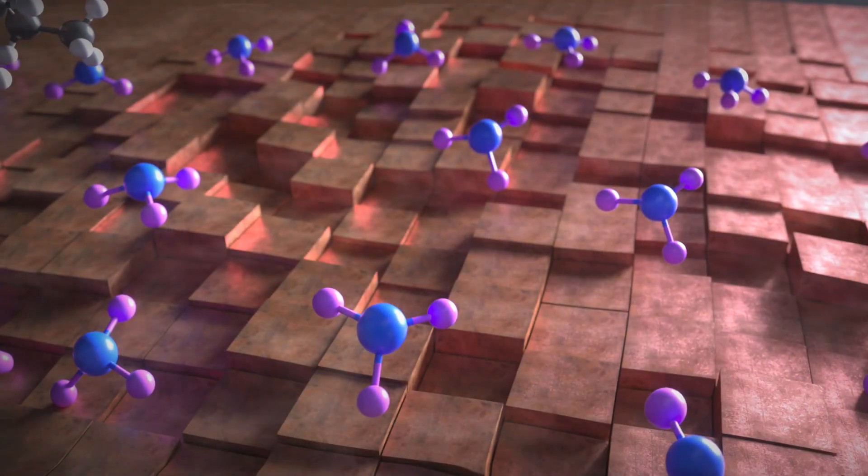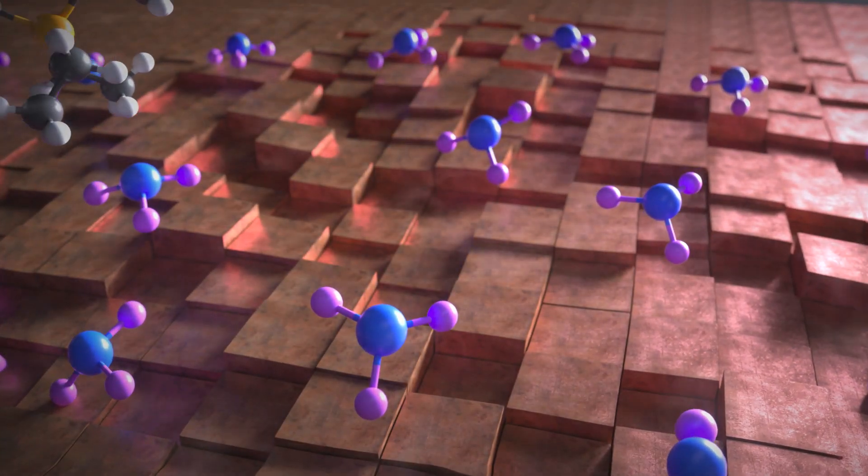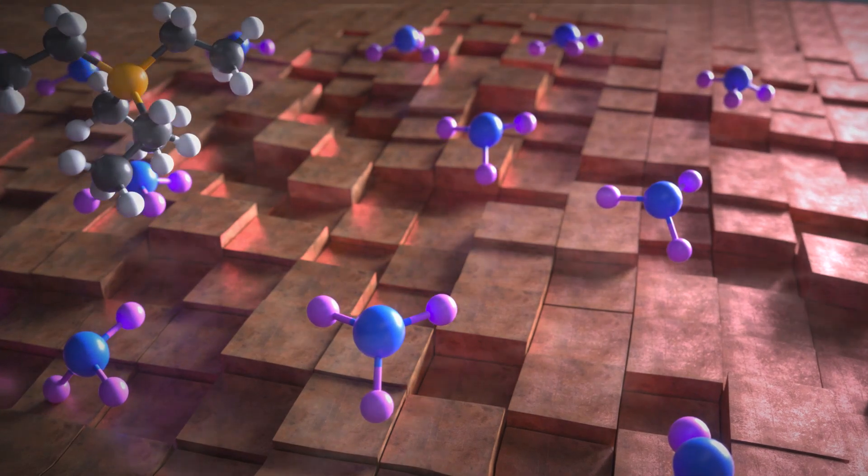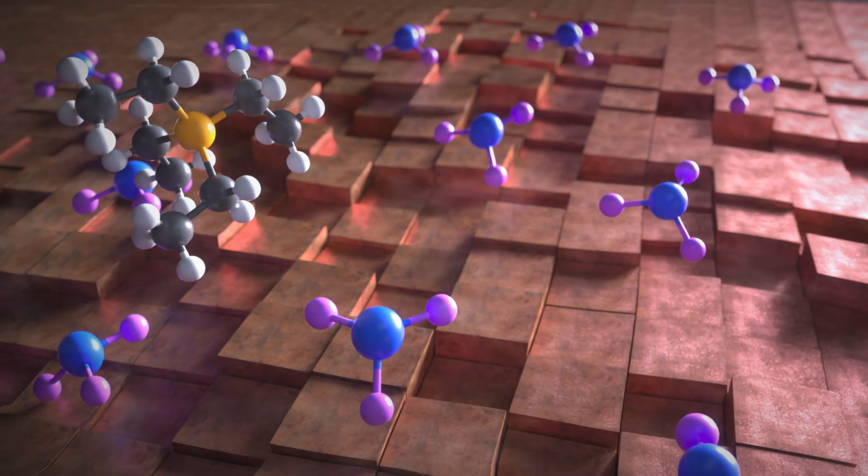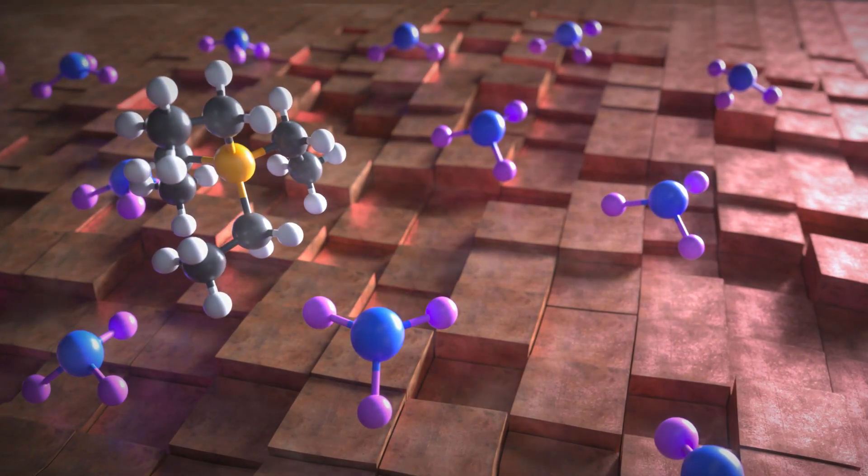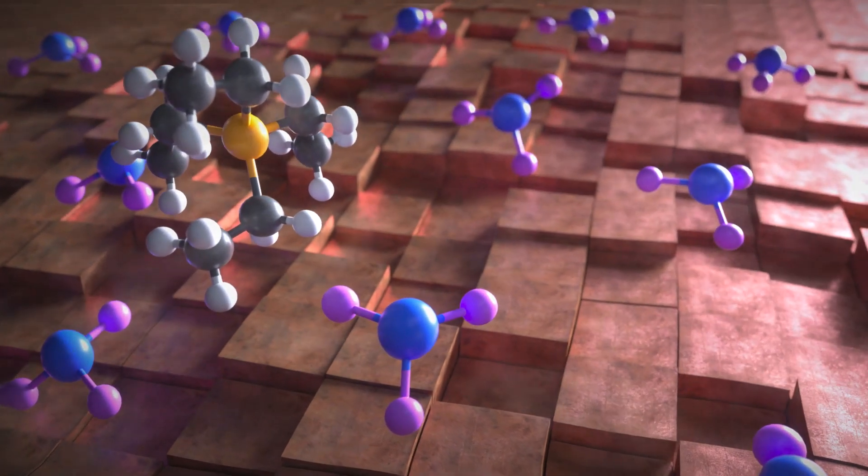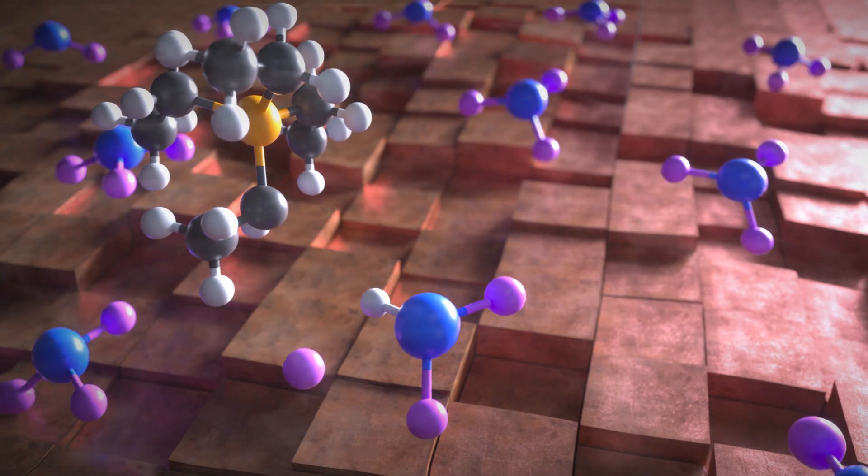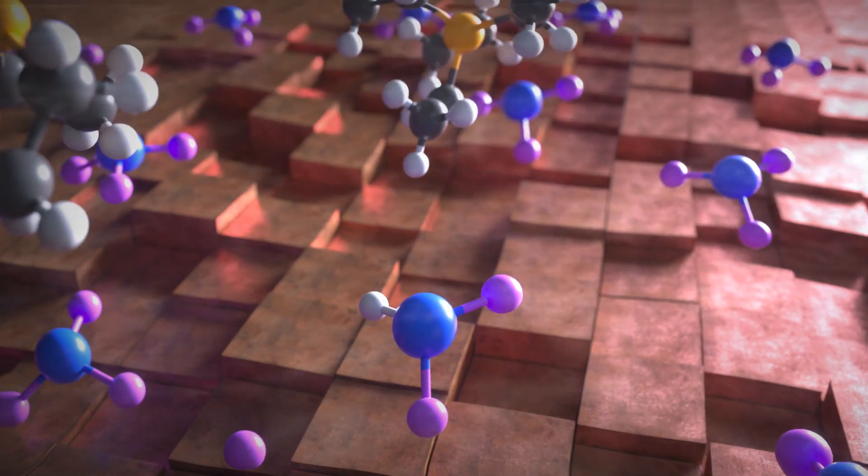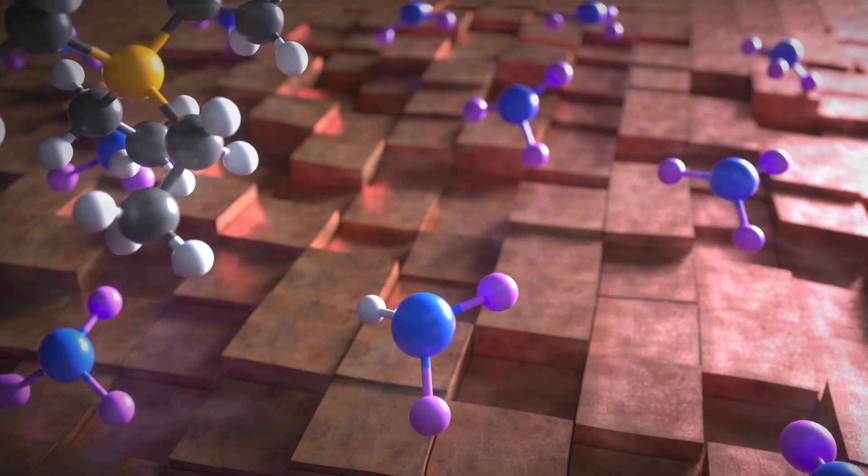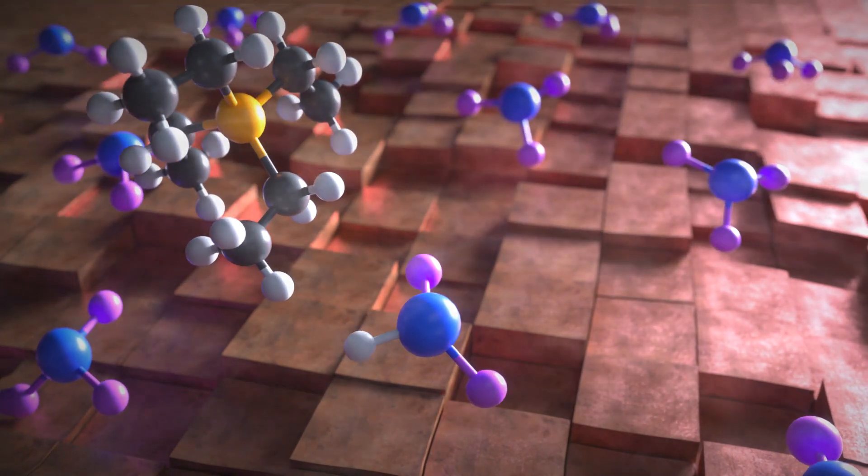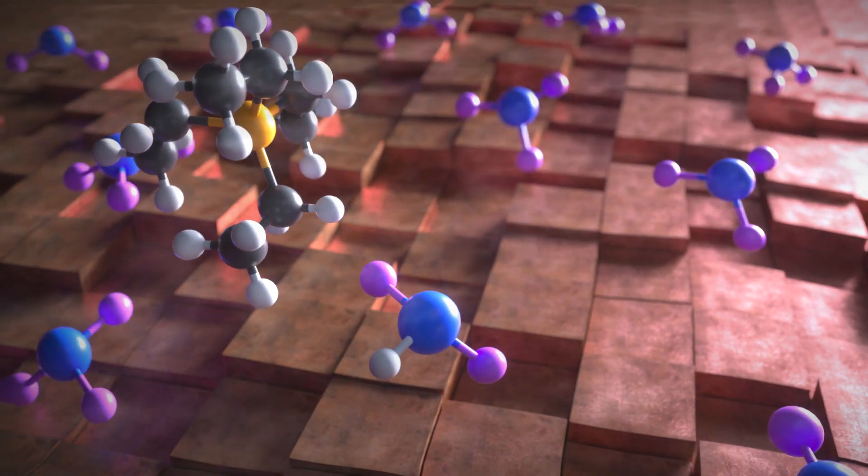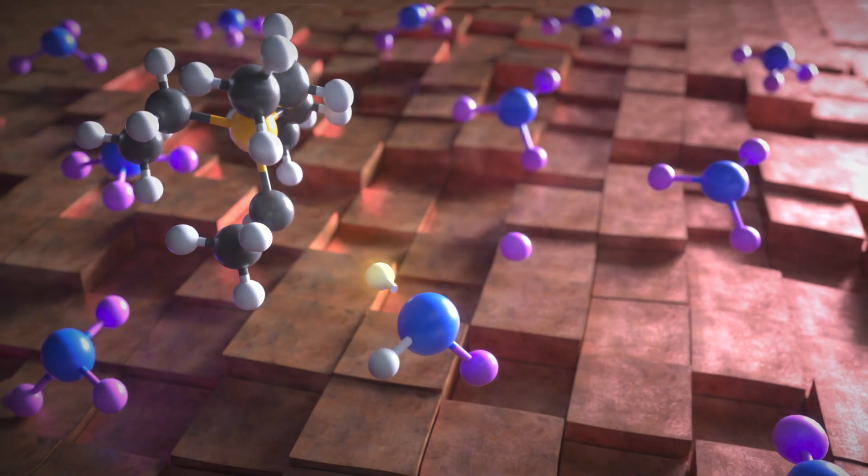At the molecular level, positively charged proton carrier is initially attracted to the negative working electrode. The electrode surface is covered with the highly reactive lithium nitride. When it reaches the surface, the proton carrier molecule releases one of its protons to the lithium nitride, in the process becoming what is known as an ylide compound. The ylide, now neutral, diffuses away, clearing the surface for a second proton carrier to deliver its proton.